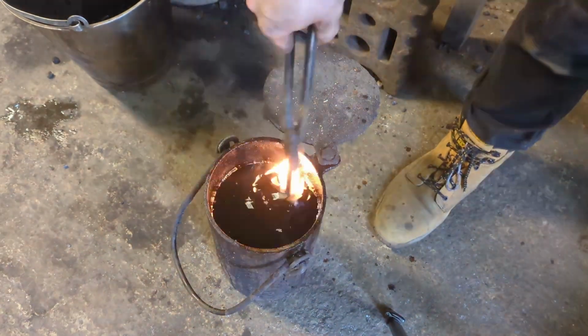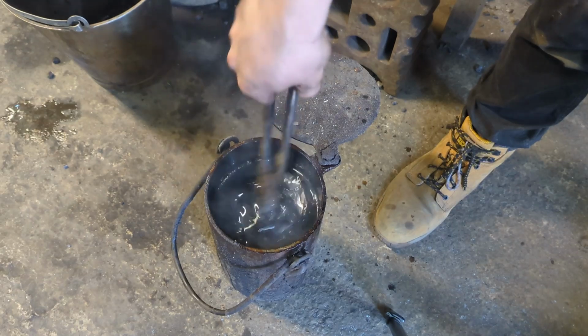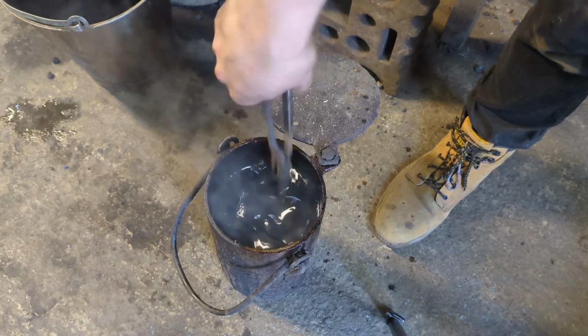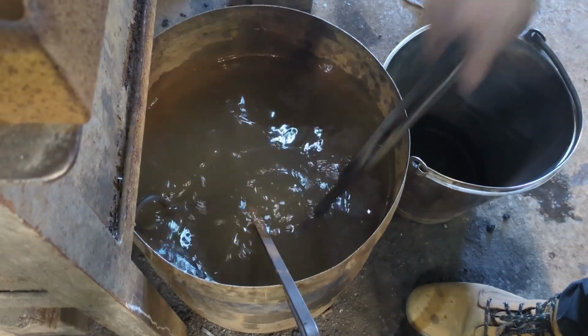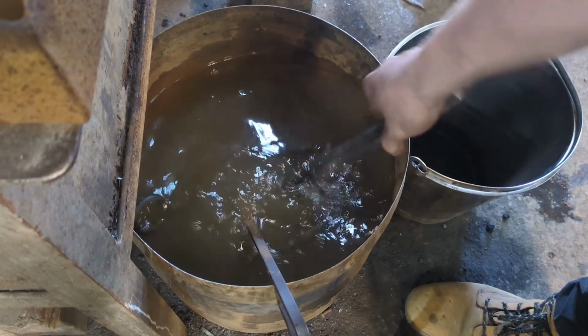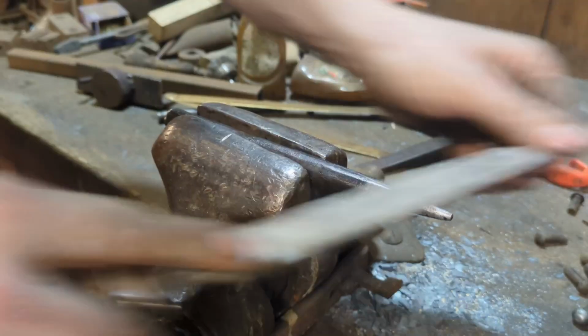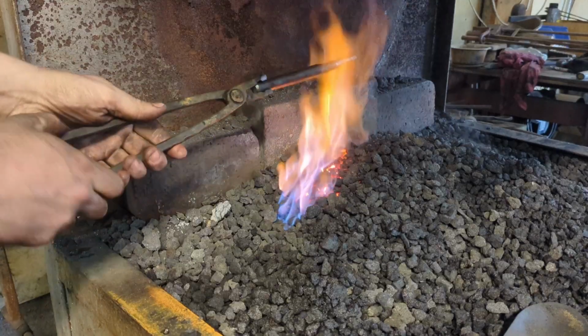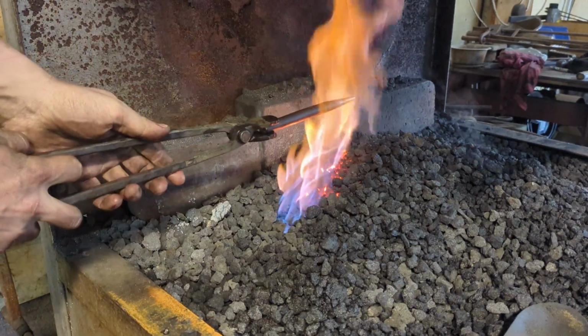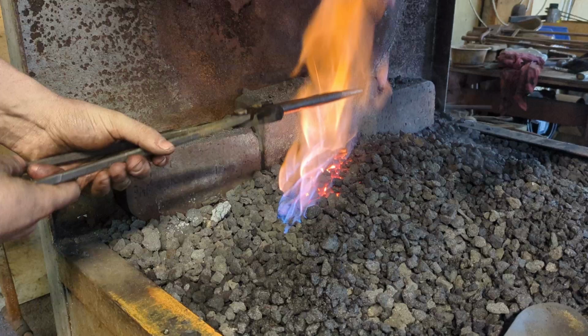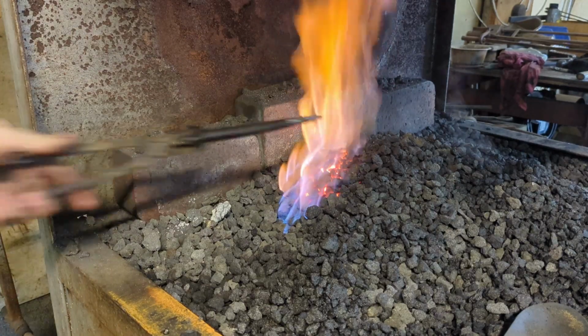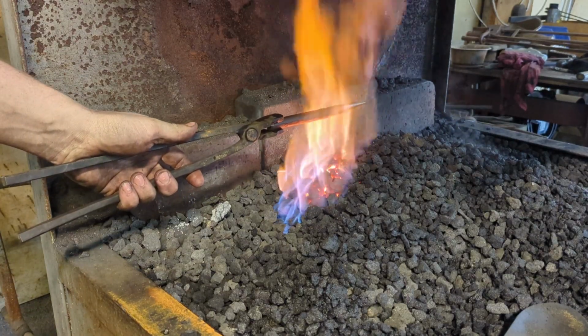Once again, heat the steel to non-magnetic and quench it, moving it around to avoid insulating air bubbles. When it's cooled to black in the oil, cool it in water so it can be handled again. We knock the scale off using a file so that we can see the temper colours. Then, by passing it back and forth through the flames, checking for the colour of the thin oxide layer, we see how much it's tempered. We're aiming for a purple colour on the end.